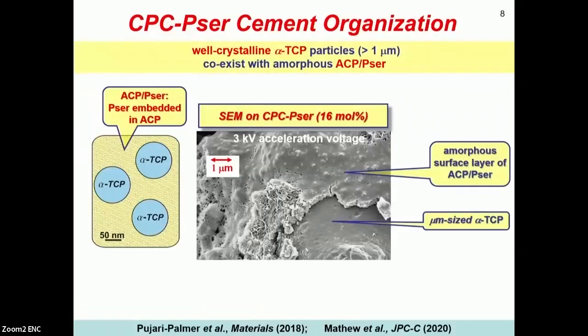So the next thing then, yes, how is the cement organization? And here we have proposed a simplified model of the cements, which consist of micrometer-sized particles of alpha TCP that coexist with this amorphous ACP PSER phase. That's the yellow color here. And that one consists of phosphoserine molecules embedded in ACP. Support for this model is also given by the scanning electron microscopy image you see here, where a micrometer-sized alpha TCP particle is coated by the amorphous ACP PSER phase.